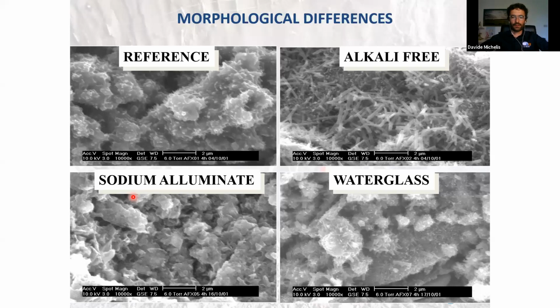Bottom left and bottom right, you see what happens with the same reference mix with sodium aluminate and water glass accelerators. You are looking at a different shape of the connections, but nothing that could be compared to the picture top right, taken with the reference accelerated with alkali free. You see that the connections and the structure between the cement particles are extremely better with the alkali free accelerator. There is a known structure. Instead, for sodium aluminate and water glass, there is something that cannot be defined as a properly defined structure between the cement particles.